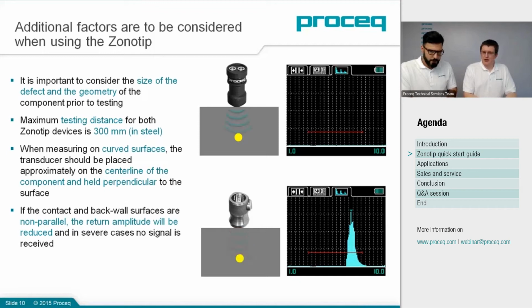And when measuring on curved surfaces, if you're using the twin, you should make sure it's aligned around the center line to get a good signal from both the transmit and receive elements. One of the main factors to consider, though, is if the front surface and the back surface are parallel. If the component is not parallel in some area, the sound will bounce away and won't be received. In some cases, it will be received very low, or the worst case, it won't be received at all. And then you can't use a thickness gauge for that.